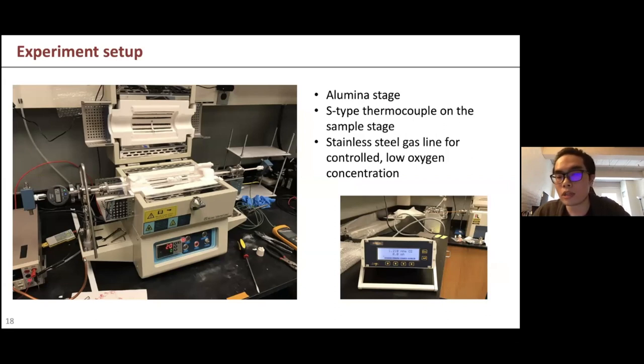So we have a stage made of alumina, so we can apply the strain at high temperature. This alumina is safe even above 1000 C. We use an S-type thermocouple just next to the sample, so we can measure the temperature accurately. And we also have very good gas control here. I'm just showing that with my setup, I can reach down to 1.2 ppm of PO2 when we are passing pure nitrogen. So basically, this is already the concentration or the purity of the gas tank.